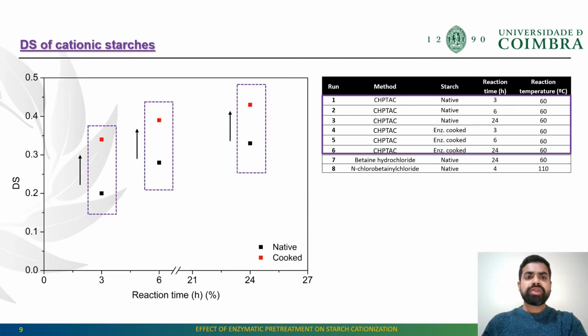Further, talking about the DS of cationic starches, this figure shows the effect of enzymatic cooking and reaction time on DS of cationic starch ether. It was observed that with the increase of reaction time from 3 to 24 hours, the DS increases from 0.2 to 0.3 using native starch as a raw material, and 0.3 to 0.4 when cooked starch was used in the reaction.